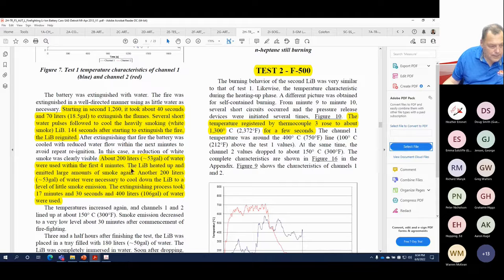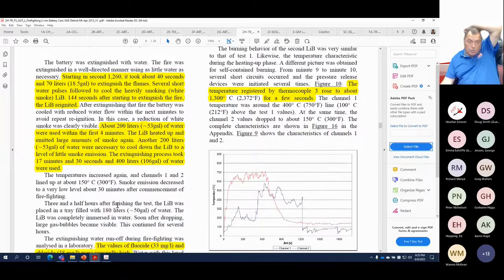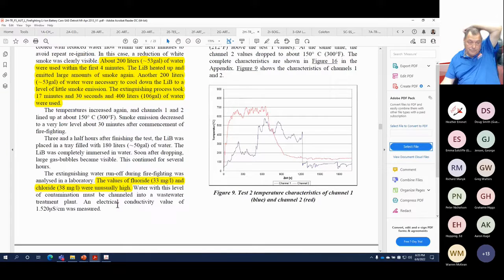The lithium-ion heated up again, emitting large amounts of smoke. Another 200 liters were necessary to cool down to the level to stop the smoke. The extinguishment took 17 minutes, 30 seconds, and 400 liters of water were used. Here they're coming back just saying the values of the fluoride and chlorides seemed unusually high here.